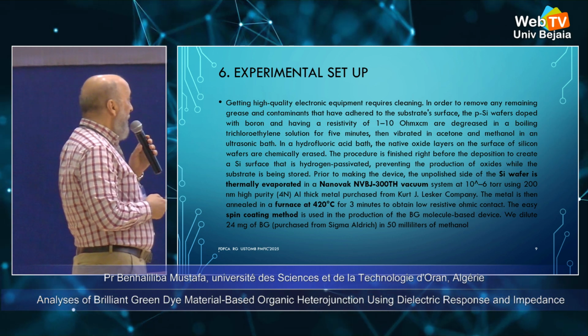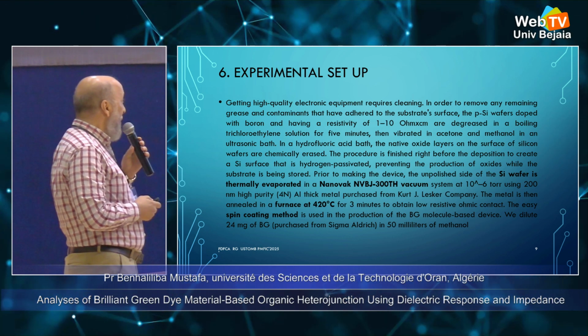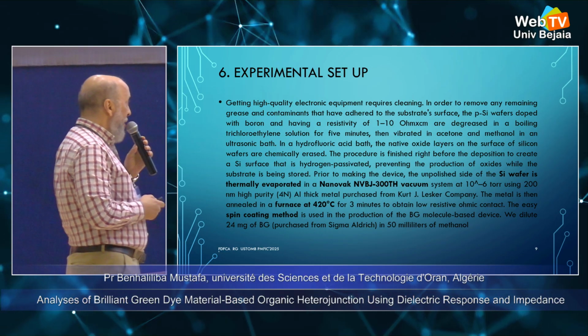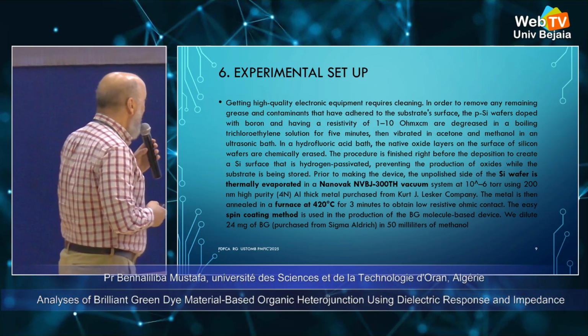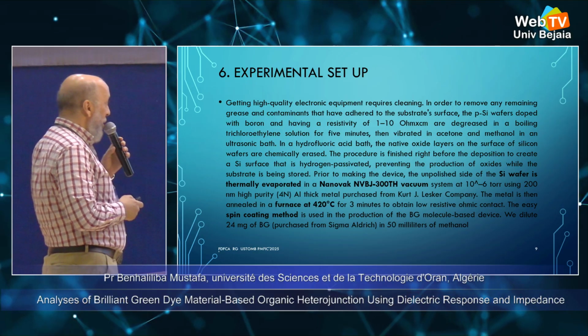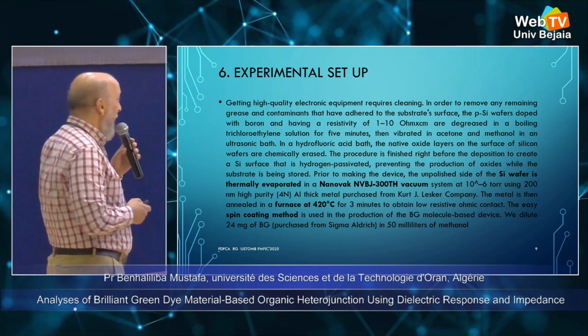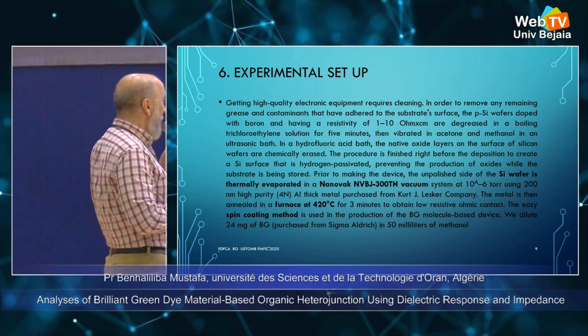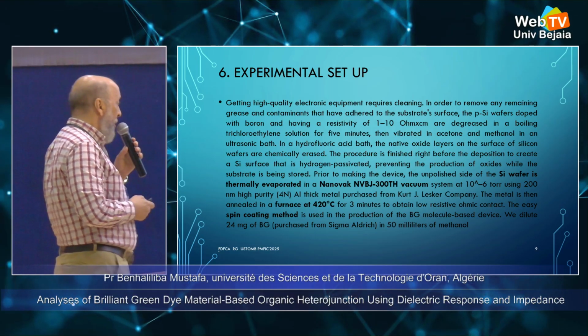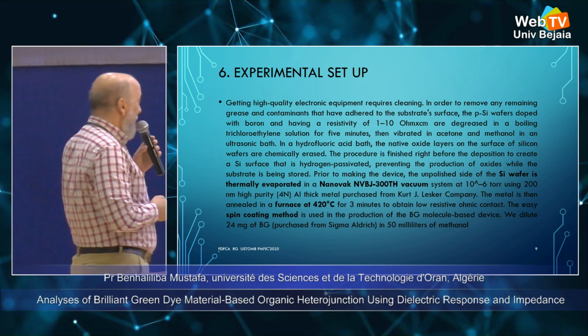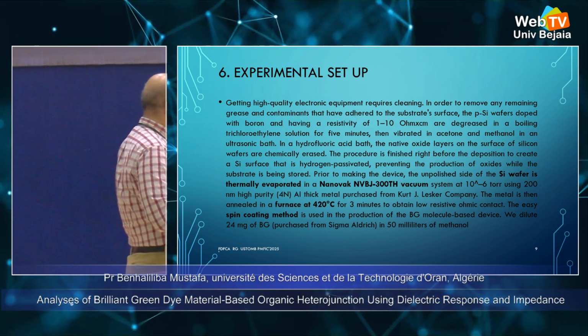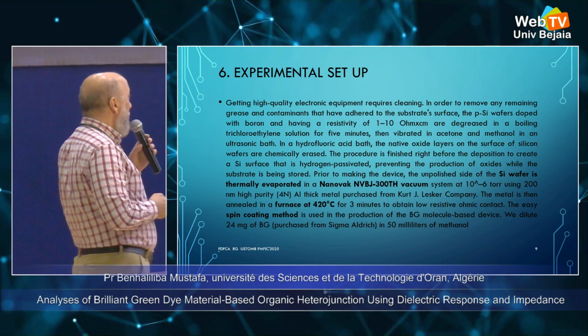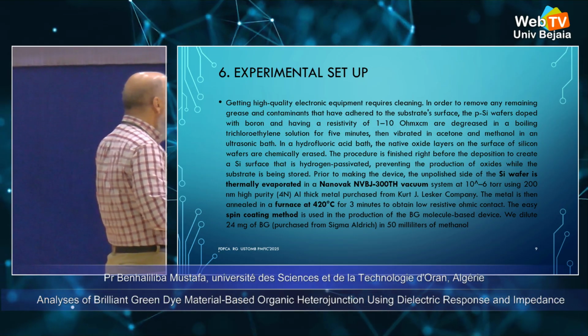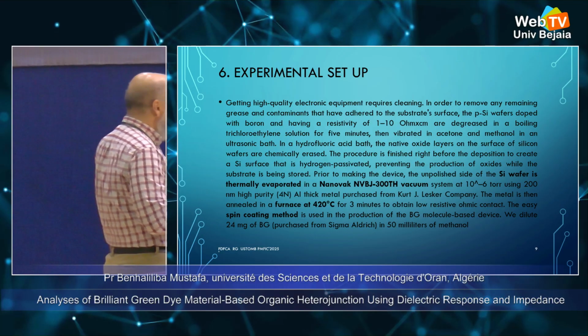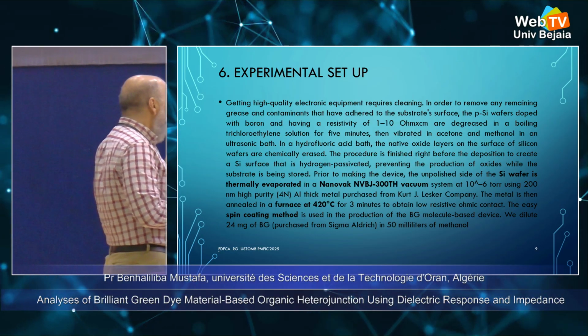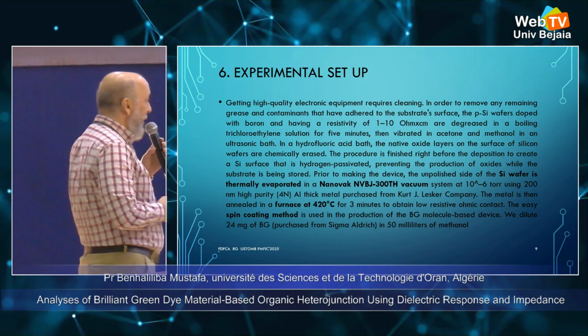In a hydrofluoric acid bath, the native oxide layer on the surface of the silicon wafer is chemically erased. The procedure is finished right before the deposition to create a hydrogen-passivated silicon surface, preventing the production of oxides while the substrate is being stored. Prior to making the device, 200 nanometer thick high purity aluminum is thermally evaporated in a vacuum system onto the unpolished side of the silicon wafer, with metals purchased from Kurt Lesker company. The metal is then annealed in a furnace at 420 degrees Celsius for 3 minutes to obtain a low resistivity ohmic contact.